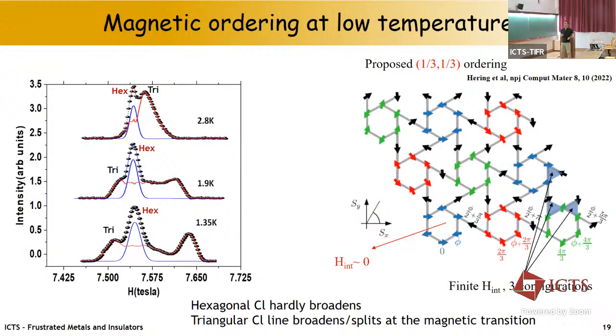Now, for the triangular side, the situation is completely different, because if you look at one triangle, the chlorine sits at the center of one of these triangles, and now we have two spins which are nearly anti-parallel, like let's say these two ones, and there is another one which is not compensated, and that's the same for all the triangles. And now there are three different triangles because there are three different orientations of the uncompensated spin. So this could indeed give rise to maybe three different peaks that we can see there.